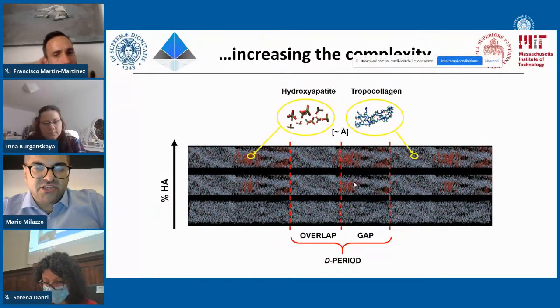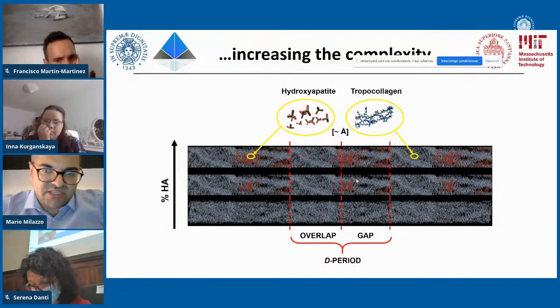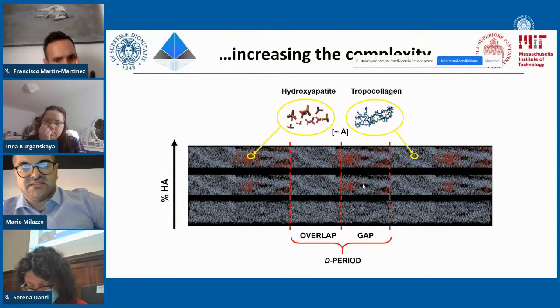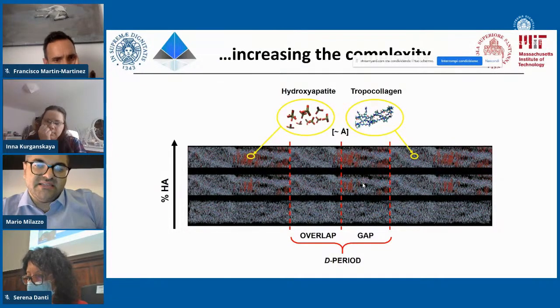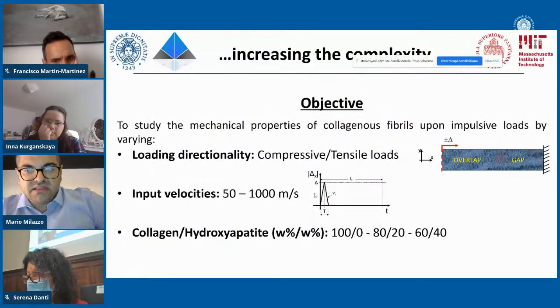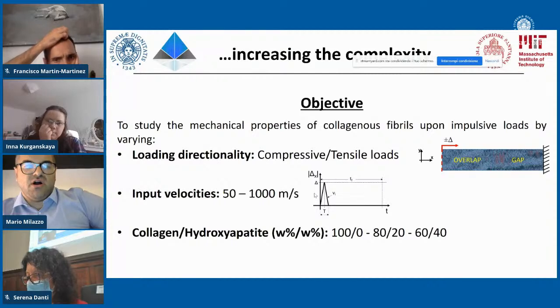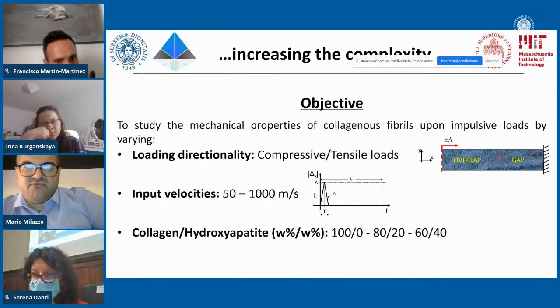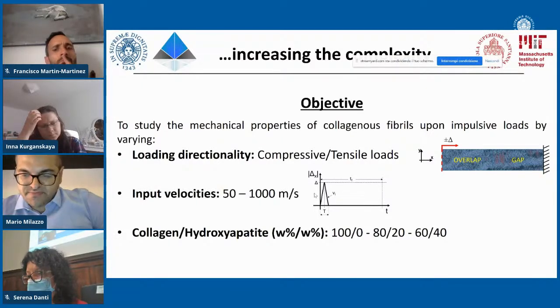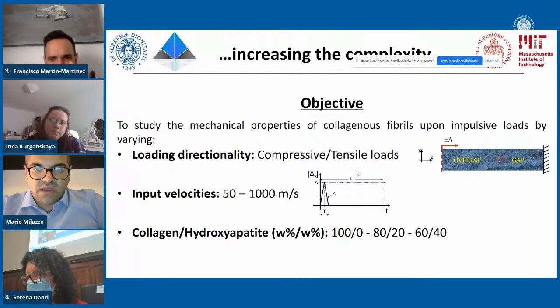And you can see in the gap region, the hydroxyapatite is mostly accumulated. So we expect also before the simulations that this region is much stiffer than the other one. In this case, we stress the structure only with compressive or tensile loads with different input velocities. And in order also to understand if a different velocity, a faster input velocity or a slower input velocity can change the behavior of the material itself.